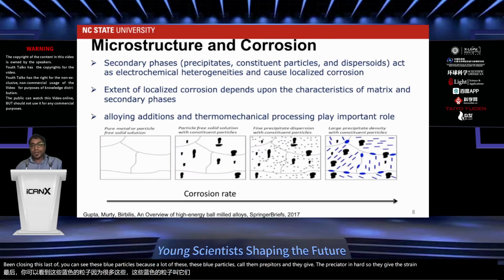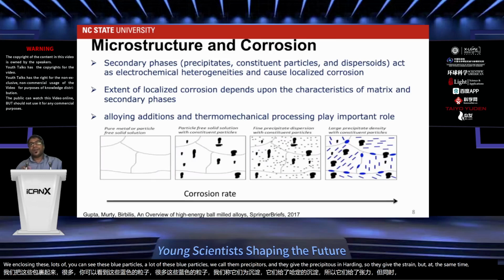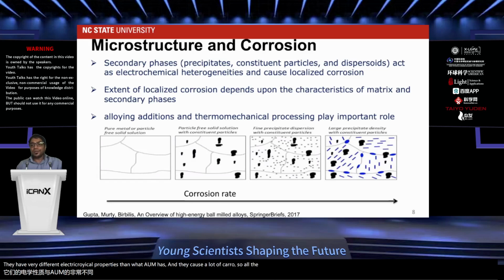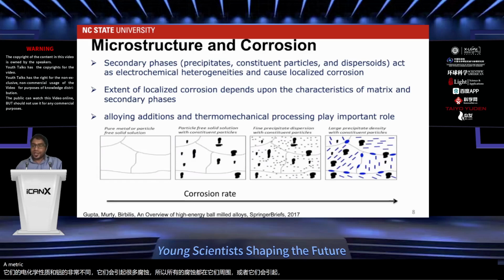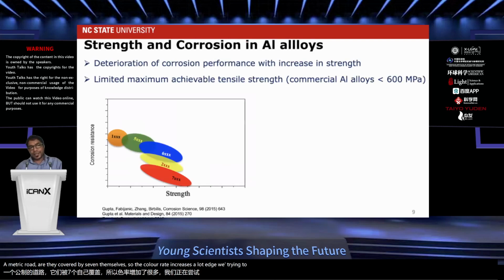So they give the strength, but at the same time, they have very different electrochemical properties than aluminum, and they cause a lot of corrosion. All the corrosion would be around them, or they would either cause the matrix to corrode or corrode by themselves. So the corrosion rate increases a lot as we try to increase the strength.